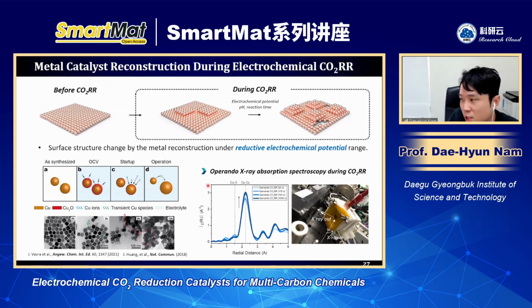Previously, it was very difficult to see this kind of reconstruction, because if we just compare the before and after states, after means there is no reductive potential, and so we need to open the cell again. It means that during this procedure, the reduced states can be reoxidized. But the important thing is we are interested in the real phase and structure during the CO2RR under the reductive potential. There is a reason why these days operando and in situ measurements are very important in CO2RR. For example, on this right-hand side, this figure shows the in situ XAS reactor which we use at the synchrotron.